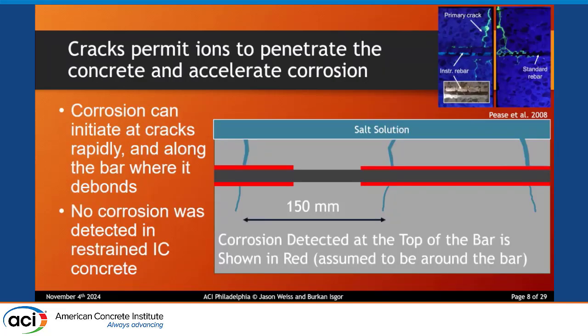So one thing I do want to mention is that many of these cracks come down to the reinforcing bar, as you see up here with the epoxy, all right, and they go along the length of the bar. So when we actually measure what's corroding, we see it's not just at the crack, it extends several inches to a foot back from the edge of where the crack is because you've now started to open up some of that debonding along the bar. So you've really created an environment where that can fill up with the de-icing salts, the de-icing solutions, and you can really start corroding a substantial portion of that bar. Again, I want to point out that the internally cured concrete, no cracks, so we're actually worried about a diffusion-based problem, which we'll talk about in a few seconds.